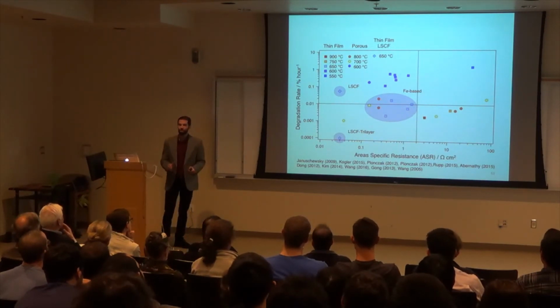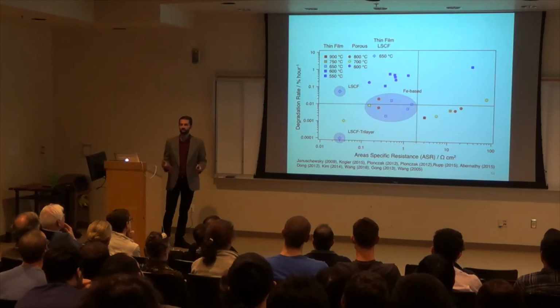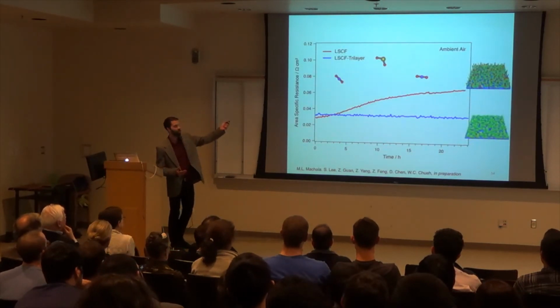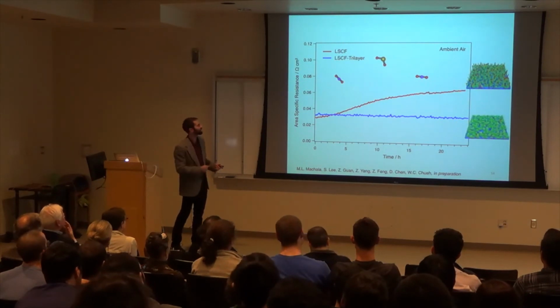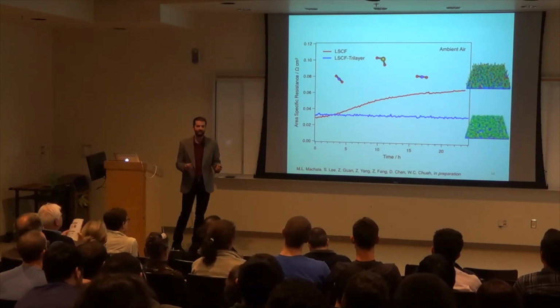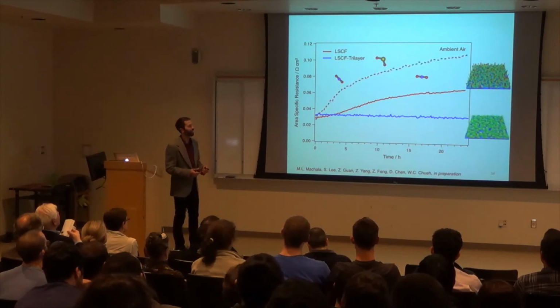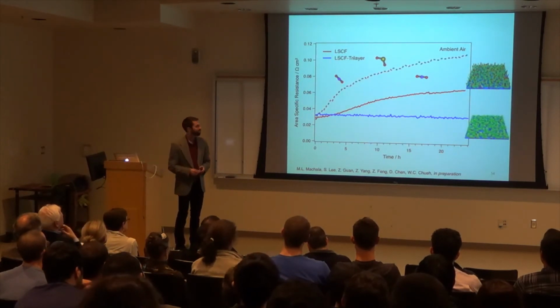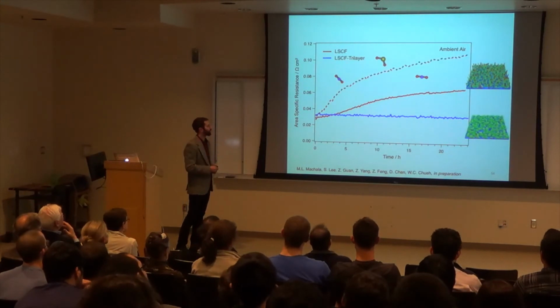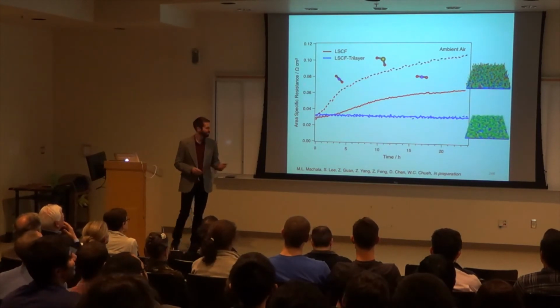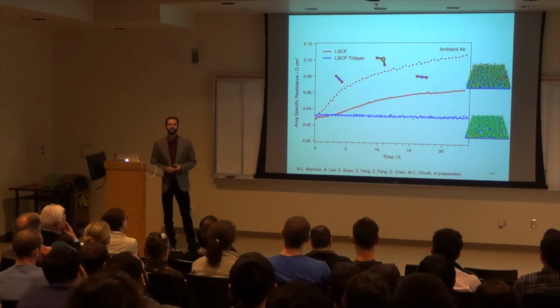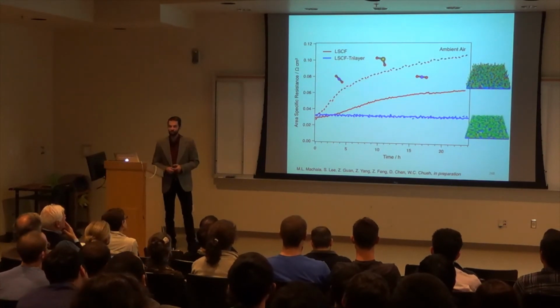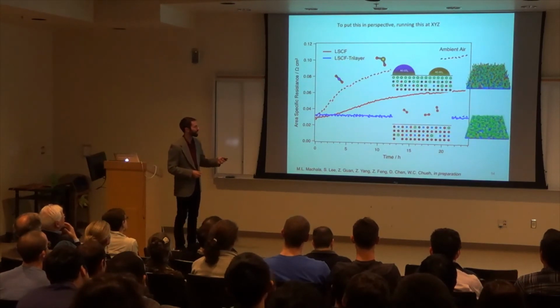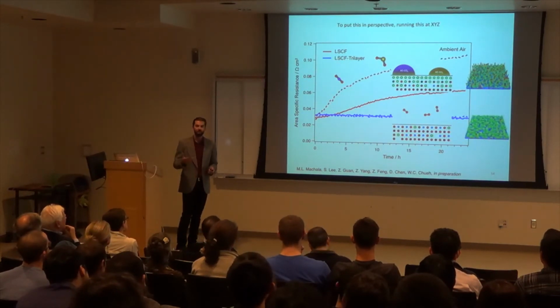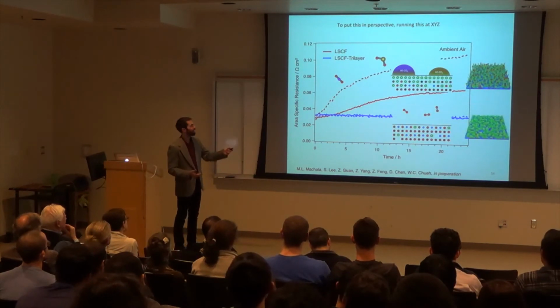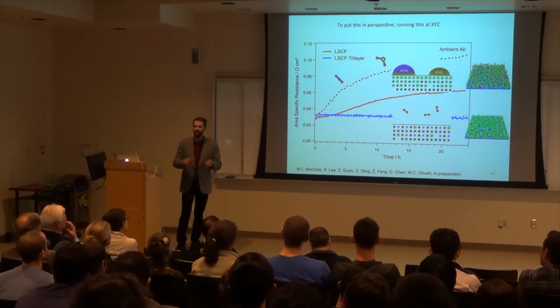So that's great. But what happens in real conditions when you have trace gases such as carbon dioxide, carbon monoxide, and sulfur oxide? So let's compare the LSCF in real ambient conditions. Well, as you might have guessed, it does degrade faster. Then when we put on the trilayer structure, we see that it essentially overlays that of the structure that we tested in the clean environment. And this basically shows us that the surface itself does not react very well with impurities in the atmosphere, and that when you have precipitates, you're further passivating the surface.